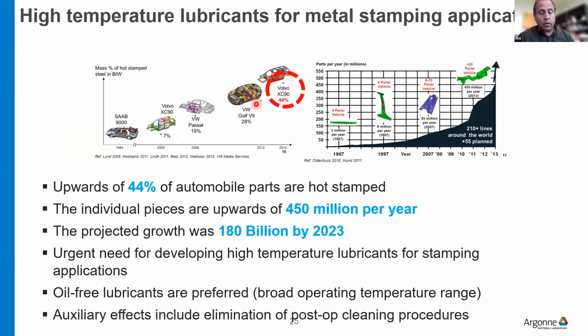Every car that you are driving right now is stamped. In every car, upwards of about 40% of the automobile parts are hot stamped. And there are individual pieces, doorknobs, and all those things, about 450 million of those per year, and the projected growth is about 180 billion. The stamped metals are mostly aluminum alloy or boron steel, and the temperature for stamping varies from 230 to 970 degrees centigrade. There are various kinds of lubricants which are developed to work at those temperatures.